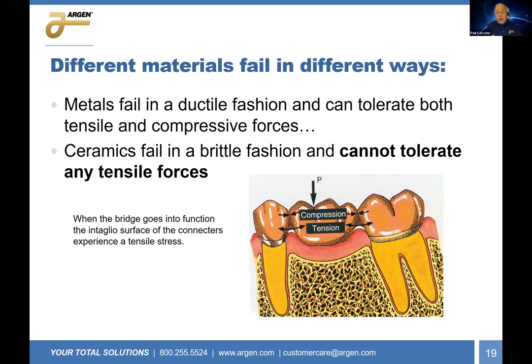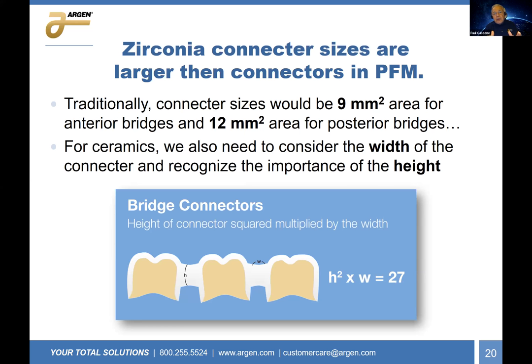Now, I spoke to you about tensile forces. Fortunately, in the mouth, most of the forces that we have are compressive, but there is one situation where you have a tensile force, and that's on the intaglio surface of a connector. So here, when this pontic goes into function, the intaglio surface goes into tension. For those of you that had used the Procera bridges, you know exactly what I'm talking about, because that's where they always fail. That requires that the laboratory change the design of the restoration from what we had in PFM to what we need for zirconia. So the bridge connectors have to be much larger than what you're used to in PFM, especially in the vertical dimension.